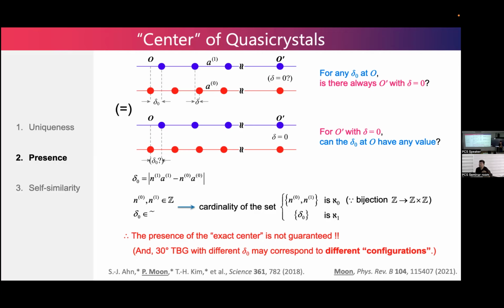Not yet, but although I studied this in a quasicrystal, this is common even to theoretical model structures, whether commensurate or incommensurate. Commensurate always has the same one, but in the incommensurate case, generally, the formula is exactly the same. The local configuration displacement is a set of real numbers, and the lattice spanned by the lattice constant is infinite, but it's left with zero.